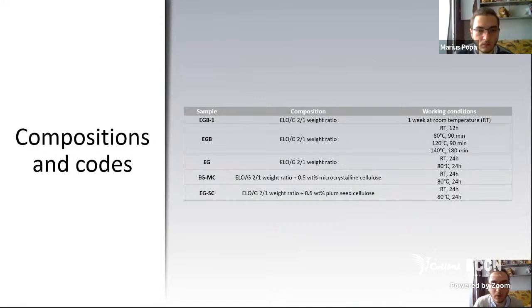For this, we used a 2 ELO to 1 hardener weight ratio under different working conditions presented in the table on the right side. And finally, we wanted to see the influence of different cellulosic components, microcrystalline cellulose, MC, and plum seed cellulose, SC, in low weight percentages on the different properties of our final products.